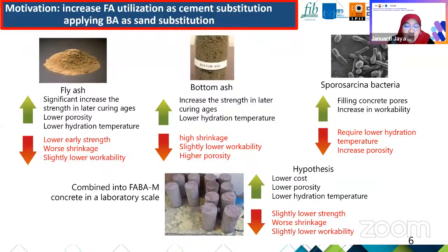However, it requires lower hydration temperature. So it is less effective actually in concrete if we put high cement content in our mixtures. At the end, our expectation here is having a lower cost concrete with lower porosity and lower hydration, and we have to see if it has a negative effect to the concrete properties.